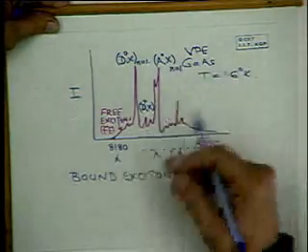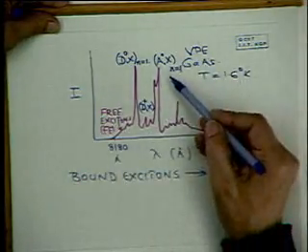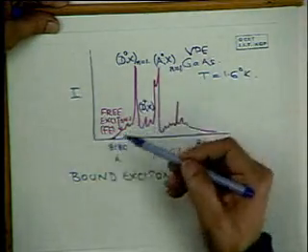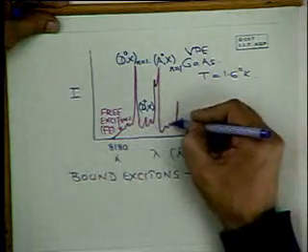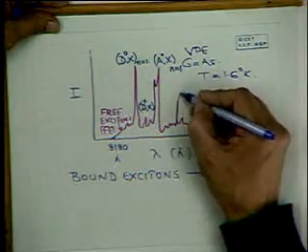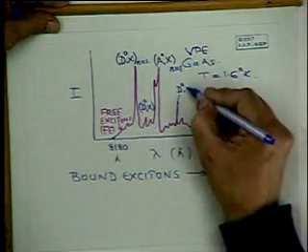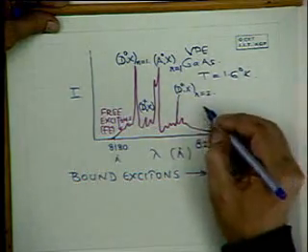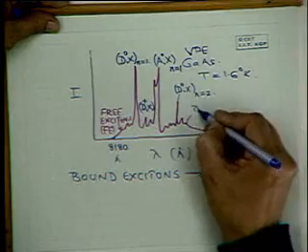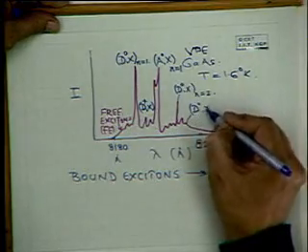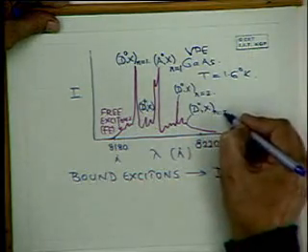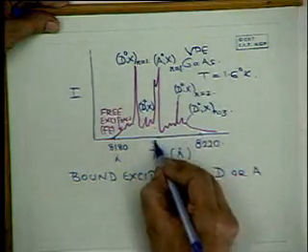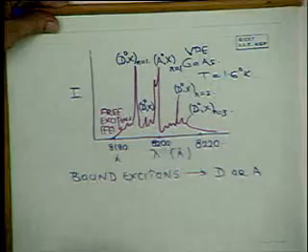Remember, excitons have hydrogen-like states with different values of n equal to 1, 2, etc. Here there is a feature, this is D0x, n is equal to 2. And finally here we have D0x, n is equal to 3. The wavelengths are typically here 8200 angstroms.